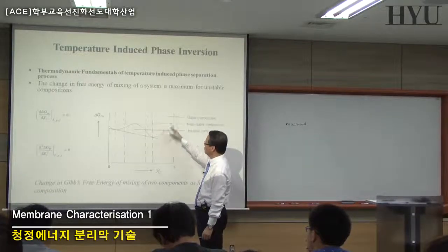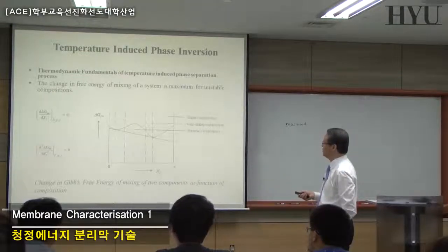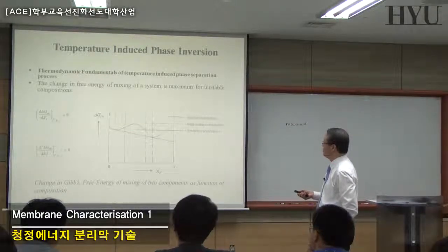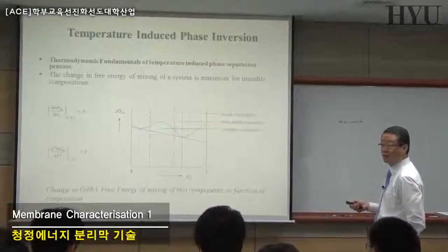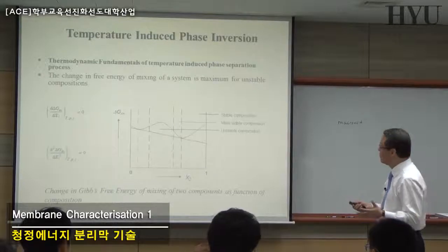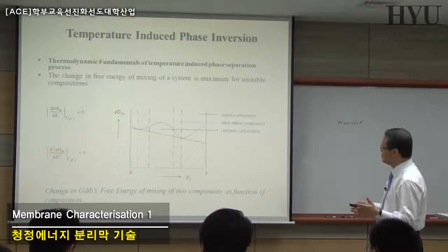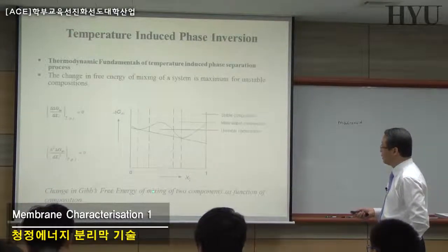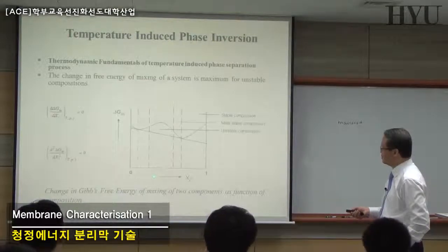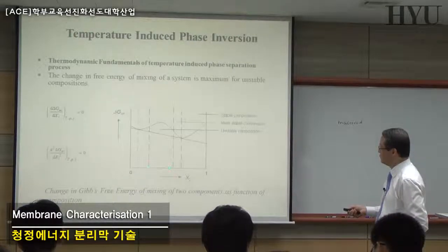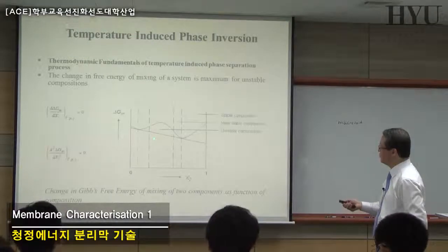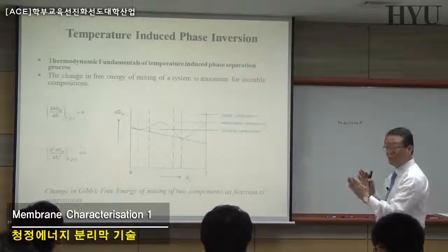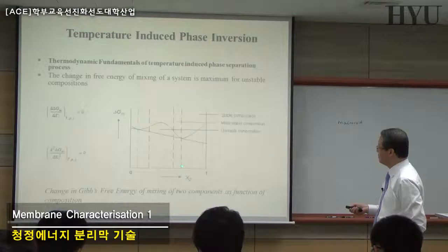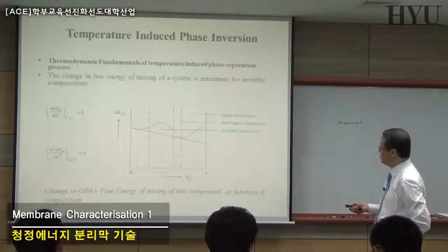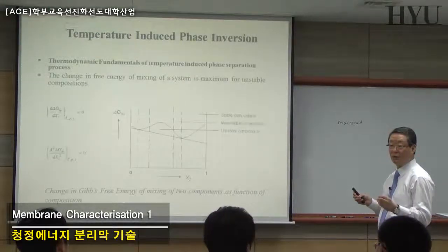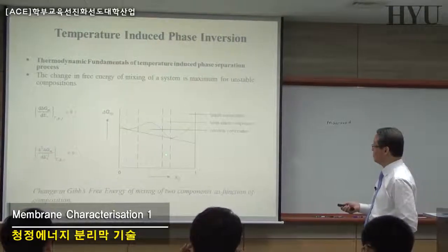So when we have a mixture, the maximum point where delta G of mixing is positive, this region is always regarded as an unstable region because we do not have any mixing stages. Whereas if delta G of mixing is negative, then this is the region where we have mixing. Now, we can find the first derivative and second derivative, and this is the region where the second derivative is equal to 0, these two regions. So in between these two, we have quite unstable regions, in between these spinodal points. Binodal points are determined right in here, and this point. And in between this binodal and spinodal, this is the region where our polymer solution is not stable, not unstable, what we call the metastable region.